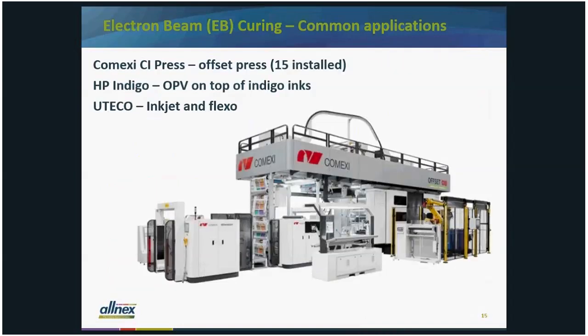So if you look at, for instance, Comexi central impression press, the offset press, globally there's about 15 that have already been installed, but they have between 5 and 10 more they're expecting to install each and every year. And the HP Indigo, these inks have a bit of wax in them. They're not heat sealable, so they need a way of protecting the ink or the finish. So there's an opportunity there in the HP Indigo space for E-beam cured OPVs because of the lack of heat that's generated.